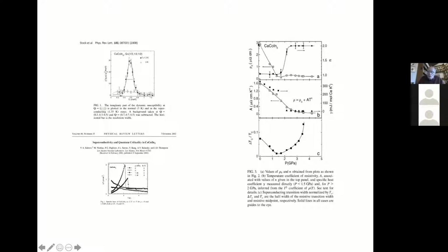That's as if what happens, what corresponds here to this establishment of the neutron resonance. We don't know what happens with pressure to this entity, but if you believe that the resistivity that one's losing below the coherence temperature in cerium cobalt indium 5, which is of order of 40 Kelvin, corresponds to resistance that would be approximately proportional to the amount of spin fluctuations that are present, then in fact